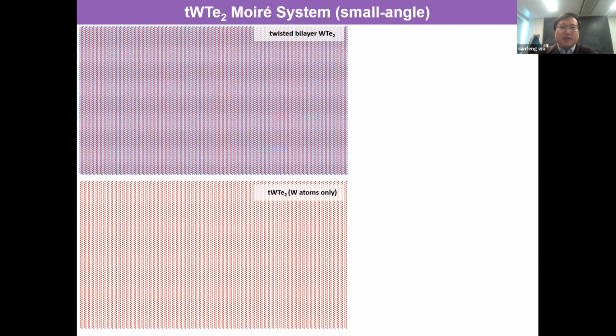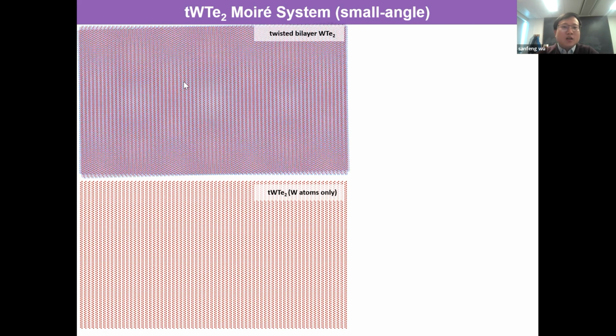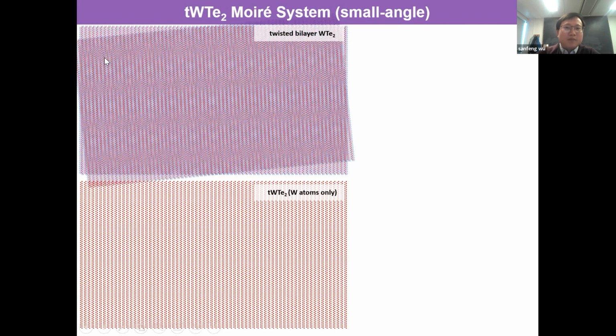What I'm showing here is a Moiré lattice, if you put two of them together with a small angle. So now you have 2 layers of tungsten ditelluride, so 6 layers of atoms. You already see the Moiré pattern here, right? It gives you stripes perpendicular to the original zigzag chain of the monolayer.